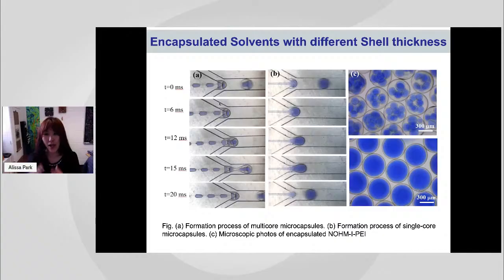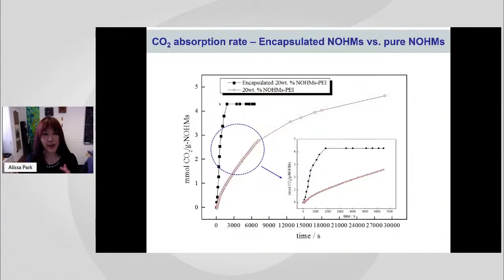If you look here, the top is a multi-core, and the bottom is single core. Usually we make these materials about 300 to 500 micron size, because bigger than that, we might have issues with the mass transfer within this microcapsule. But these microcapsules are really excellent because you're combining the benefits of liquid solvents and solid sorbents. So now reactor design can be a lot more flexible, and we have definitely much higher interface area, and that reflects in the reaction kinetics, how fast you can capture CO2 using these materials.